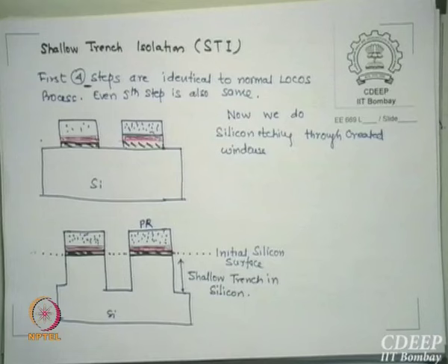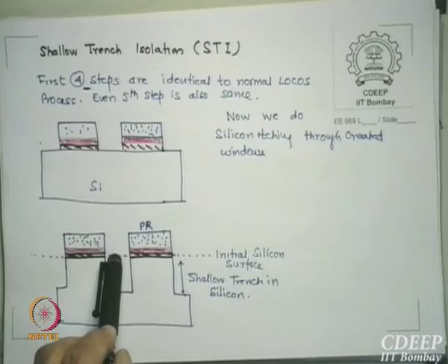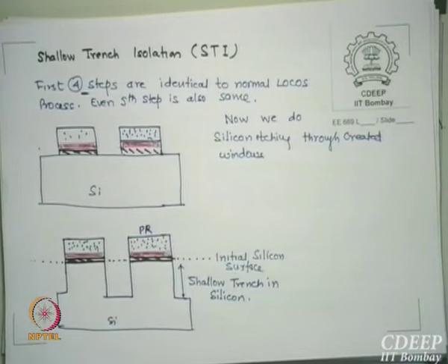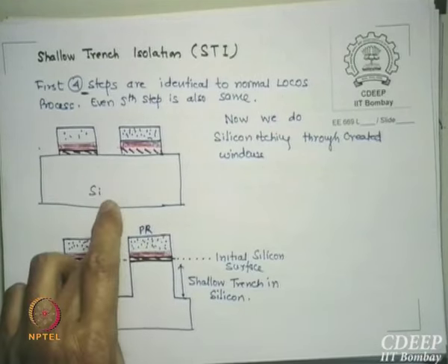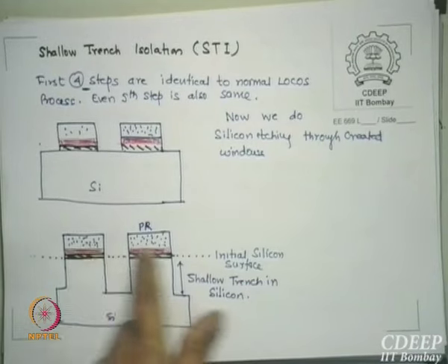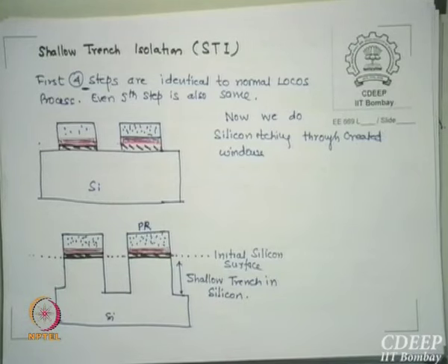Here I do a process of etching which is exactly vertical, which is called anisotropic etching. Dry etching, as the word suggests; wet etching is always isotropic. Anisotropic etching is done by dry etching, so we will do dry etching. So this area of silicon has been removed, this area has been removed, and this area has been taken away. So now I have oxide nitride base and you have trenches sidewise. Is that clear? These islands are now sitting just above the trenches.